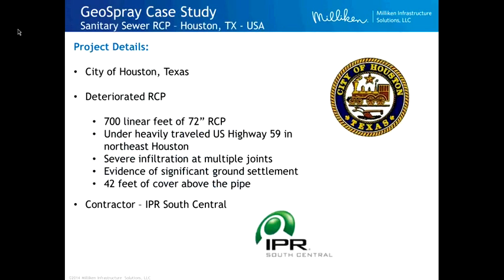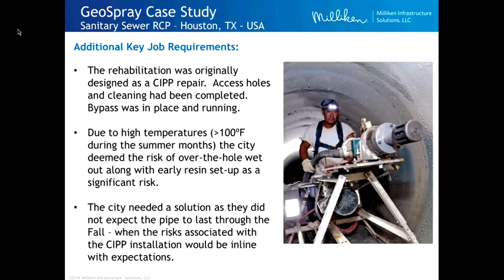This is a sanitary sewer in Houston, Texas. It was a 72-inch. You can see it was under a 4-lane highway, and it was under 42 feet of fill. This was originally designed and bid as a cured-in-place project. But what happened is, in Houston, in the summertime, it gets pretty hot. The temperatures rose above 100 degrees, and they were concerned that the cured-in-place bags would kick off too quickly as they were wetting out over site, and they were afraid that the temperatures would cause them to start setting up before they got them fully placed inside the sewer.